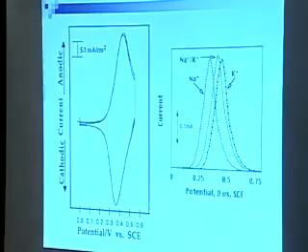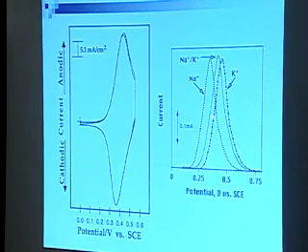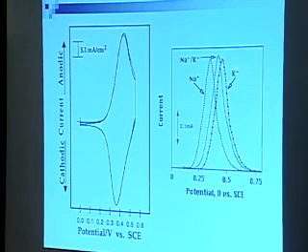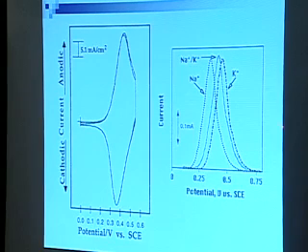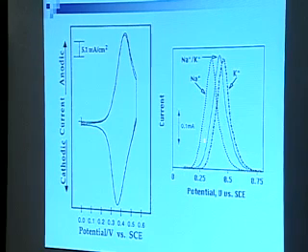And so we said, we have these electrodes. You throw them into the sodium and potassium, we'll see it. We know, this is just a simulation over here, the top half of the cyclic voltammogram. We know that in pure sodium, a CV will look like that, top half of it, and in pure potassium, we know it'll look like that. I showed you that. And so there's 150 millivolts in between those two, and we expect a wave in between, and this is the simulation of that gray wave, and we'll pick it out. There's no way you can miss that.